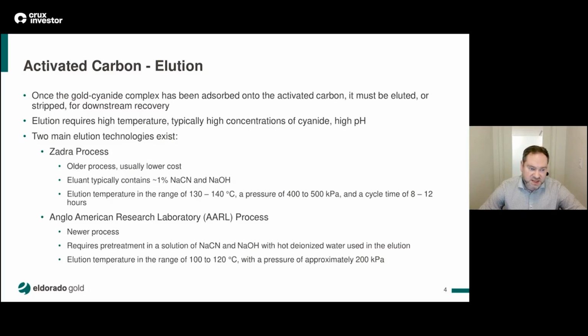Developed more recently than the Zadra process, but it has been around for quite a long time as well. The carbon is pre-treated in a solution of sodium cyanide and sodium hydroxide, and then hot deionized water is used in the elution stage. Somewhat lower temperatures and lower pressures than the Zadra process, but higher requirements for that deionized water in terms of its purity.